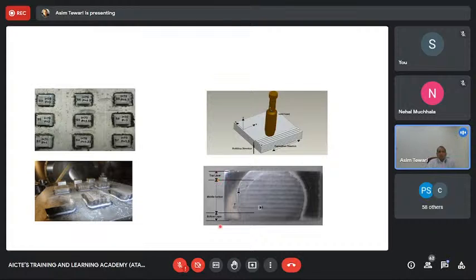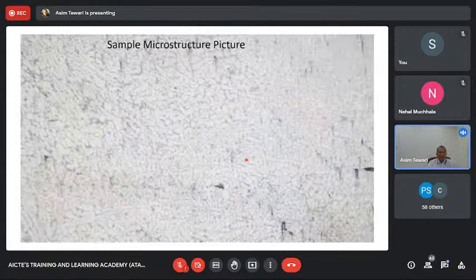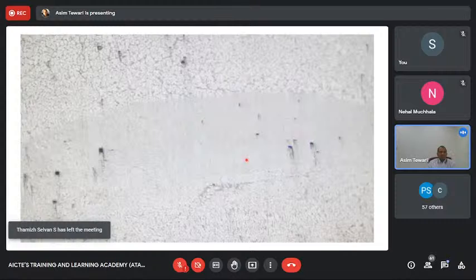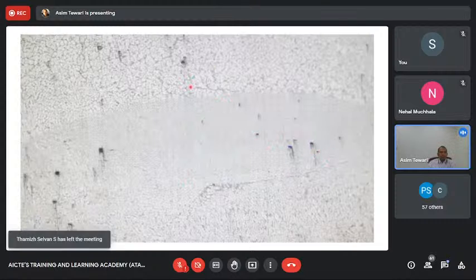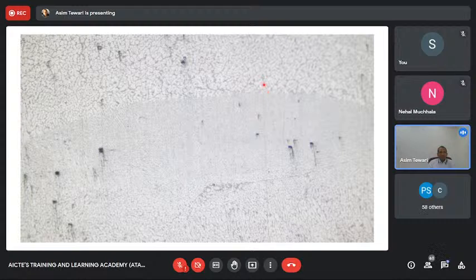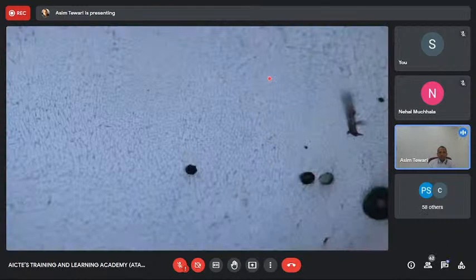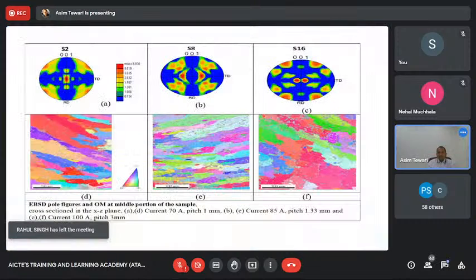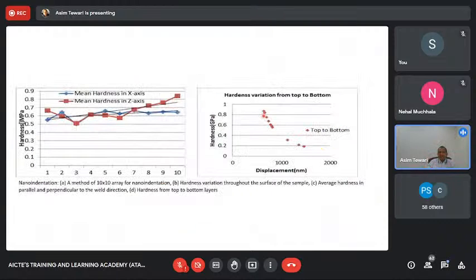Now, this is just to show you one specific case in which we are adding material layer by layer through our additive process. And these are the individual pieces which have been generated by additive manufacturing. And you can see the layers as you go from one to the other end. And we can now measure the microstructures. And this is showing you some porosity there. This is showing you a microstructure variation, fine microstructure, coarse microstructure, huge porosities. This is how the individual grains look. And they are, of course, distorted and elongated.